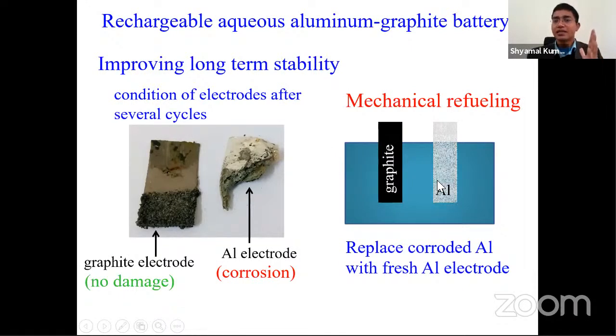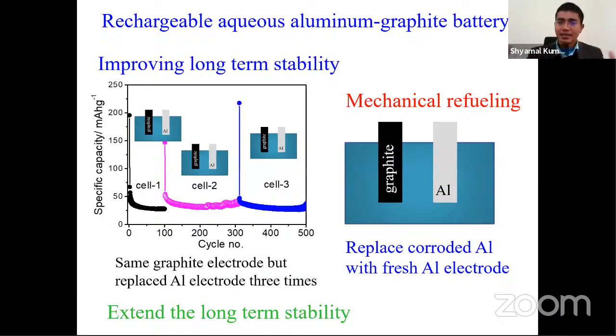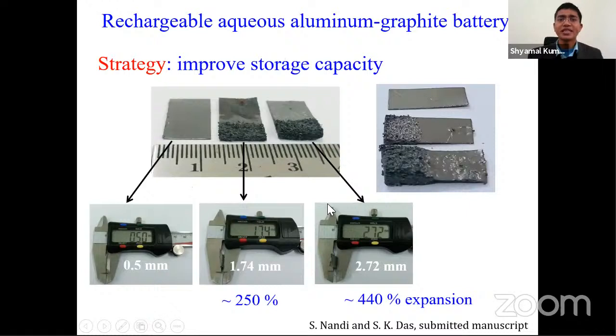With time, what is happening? There is corrosion of the aluminum foil. So what we can do is replace this corroded aluminum foil with a fresh piece of aluminum. That is how we could extend the cycle number. As you can see in this plot, we have 3 different cells, but we use the same graphite foil and 3 different aluminum electrodes, and we could run the cells for larger and larger numbers of cycles.